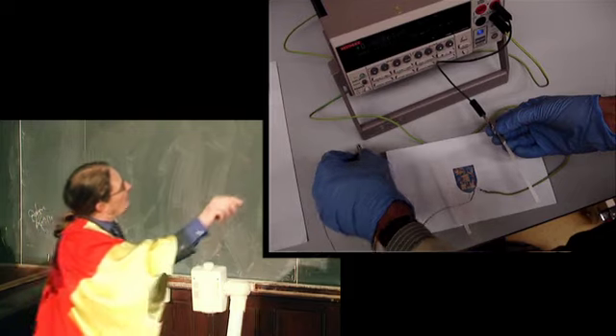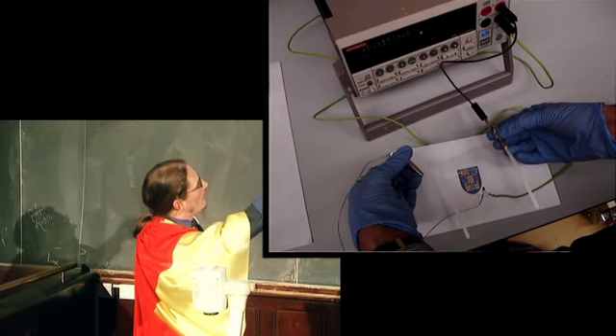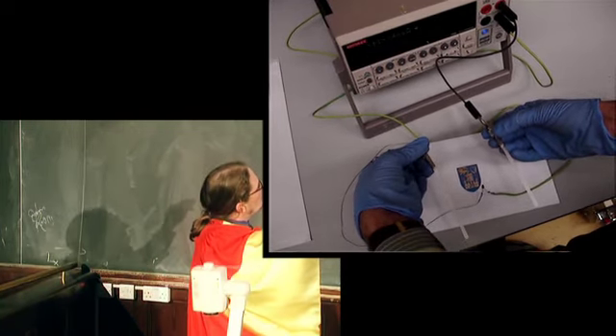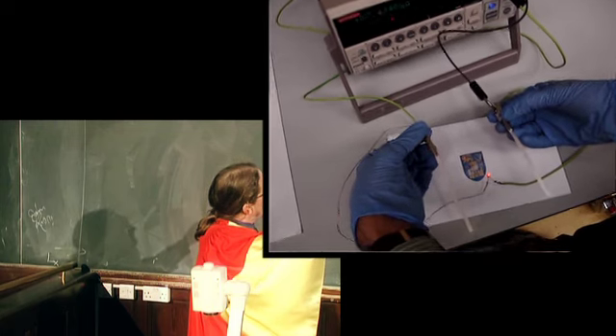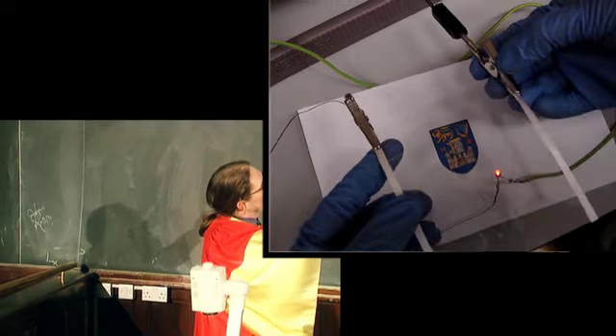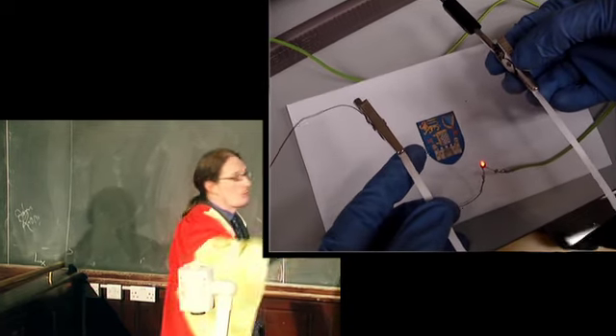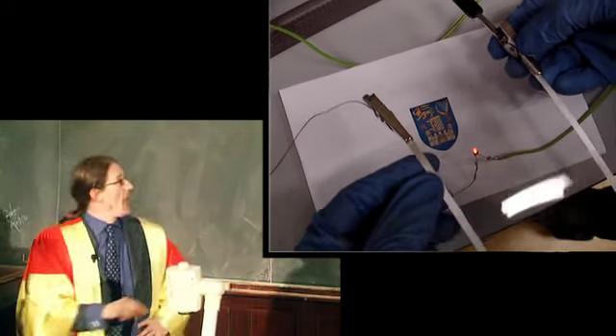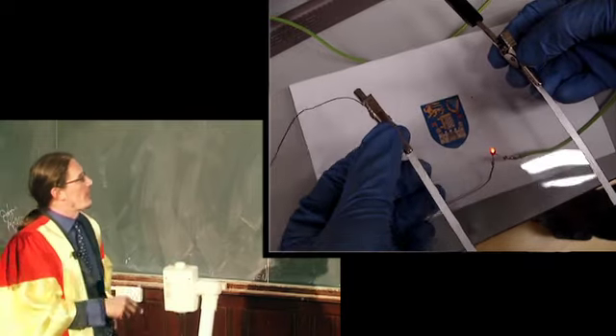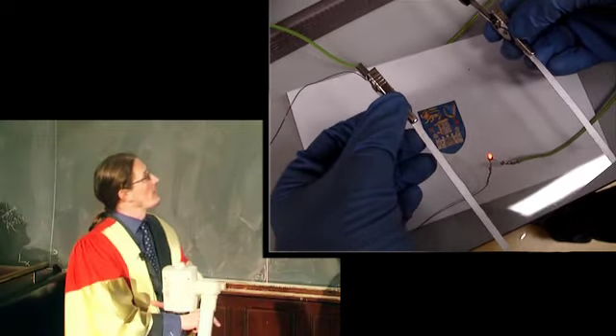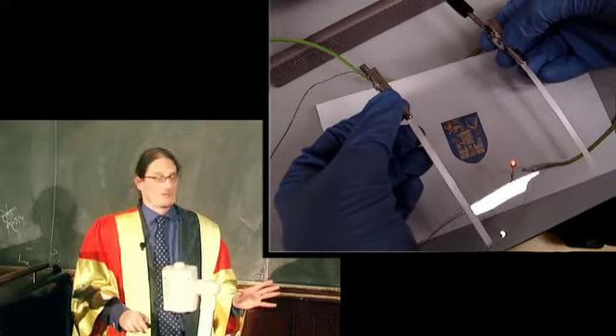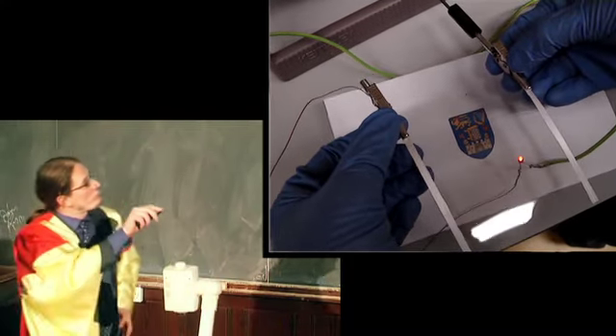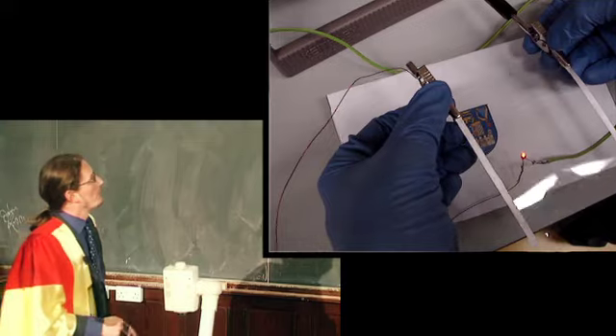This is a film of silver nanowires on a plastic surface. There's an electric circuit going into a power supply through an LED. When you connect the circuit up there, the light goes on. The current driving that device is flowing through this transparent piece of plastic. And when you bend the piece of plastic, the light stays on. If that was indium tin oxide, the light would turn out because the electrode would break as soon as it was bent. So this really shows that this does indeed work.